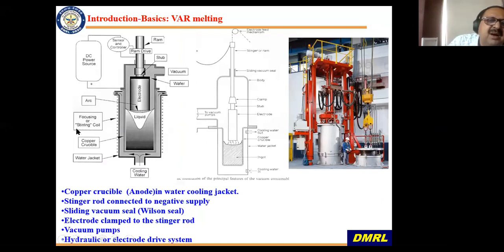This is just a schematic of a VAR melting process. Here I'm showing a consumable melting. This is called a stinger rod, and this whole thing is enclosed in vacuum. Here you have the vacuum pump. Here you have the electrode. The same thing is shown here also, and this is a copper crucible which is water cooled from outside. Here the water comes in and goes out, and by arcing, you are melting, and then it is depositing in the crucible, and then slowly this is lowered, and the electrode gets consumed and gets solidified in the copper crucible. Here I am just showing one industrial furnace which is underground, so you can see the top part of it.